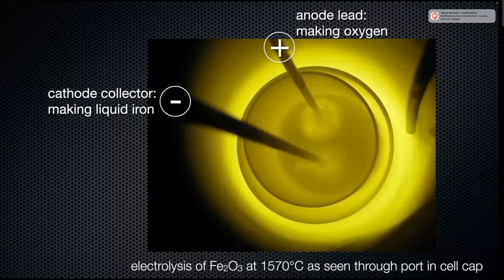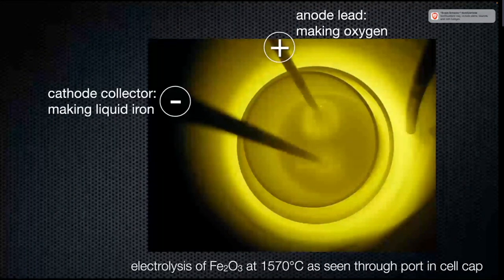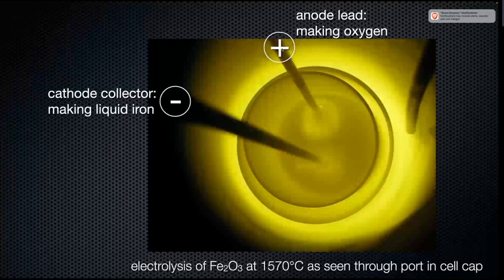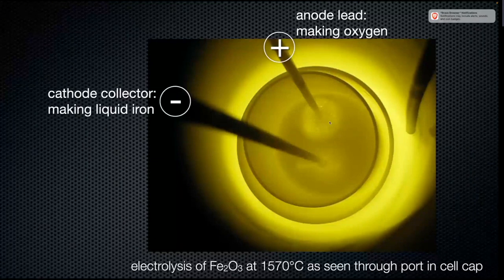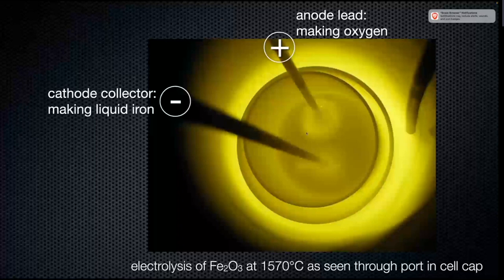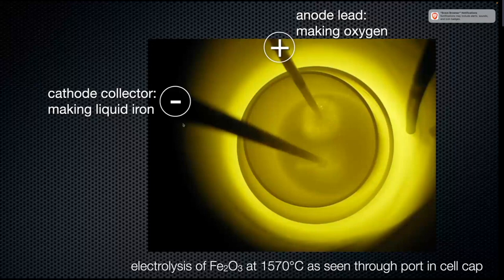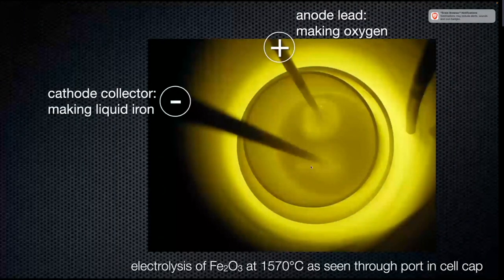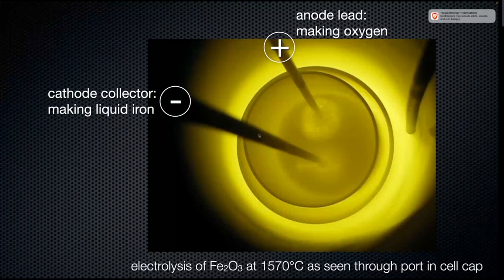So I'm going to show you what happens if you look through the camera. So this is 1600 degrees Celsius. And now we're going to look through the camera. And so you can see the plus. This is the anode. And this anode probably at the time was made out of platinum group metal, maybe platinum or iridium. And you will see the gas oxygen bubbles coming off on the anode. And then the negative, this is the cathode. And the cathode is the molybdenum plate. You can see the molybdenum plate, which is positioned vertically. It's connected to the cathode current collector.